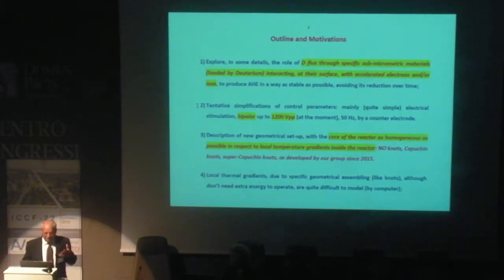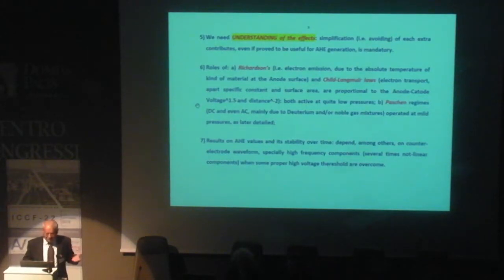To study the effect of only the voltage to stimulate flux, we make a step down from the previous experiment. In the previous experiment, we used geometry to promote non-equilibrium condition. Now we remove any thermal discontinuity, and we just focus on voltage effect. So at that time we developed knots, Capuchin knots, and so on. So now the system is locally as homogeneous as possible. We identify only one parameter. The main thing is we want to understand the effect. So oversimplification is the only possibility.